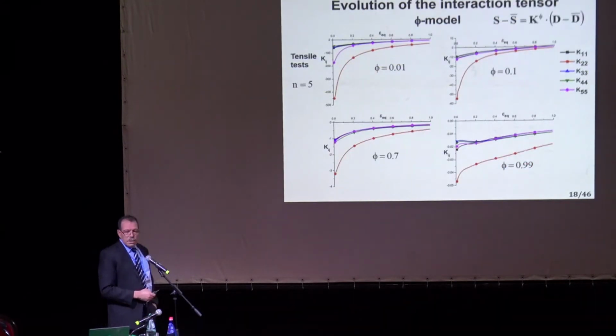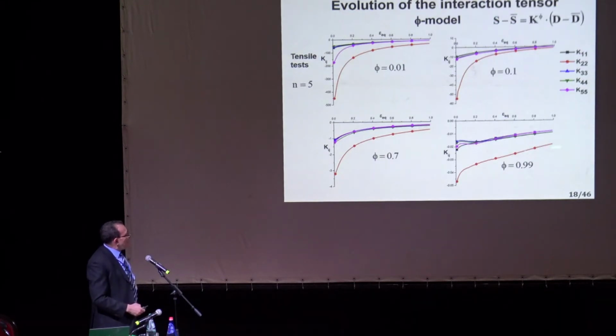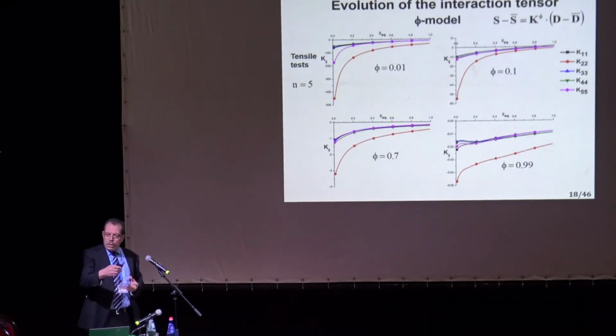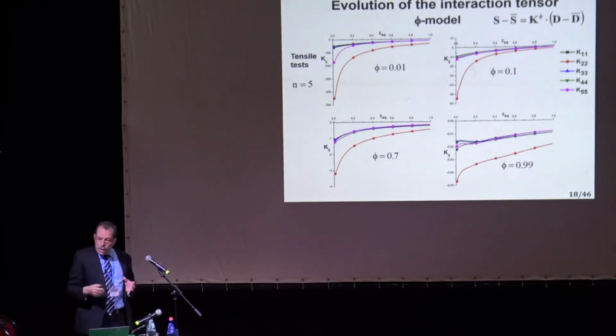Now, let me plot these two interaction tensors, for the phi model and for the self-consistent, and I'm taking the power law coefficient to be 5, which in strain rate sensitivity is 1/5, and I'm taking phi equal to 0.01, which is close to the upper bound, and phi equal to 0.99, which is close to the lower bound. Okay, so what you should notice here is not necessarily how these things evolve, but the values. Look at the values of k. They are of the order of 200, negative 200, for upper bound. When we get close to the lower bound, they are very, very small. And in between, of course, they are dropping. Which means that as phi gets smaller, closer to the upper bound, the k is huge, so huge interactions.